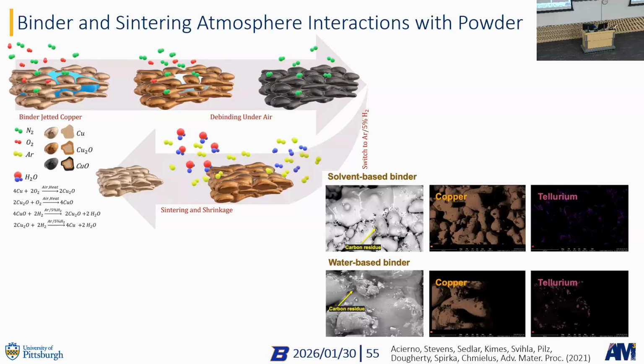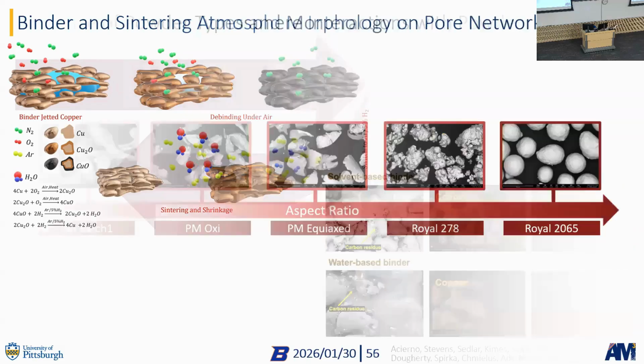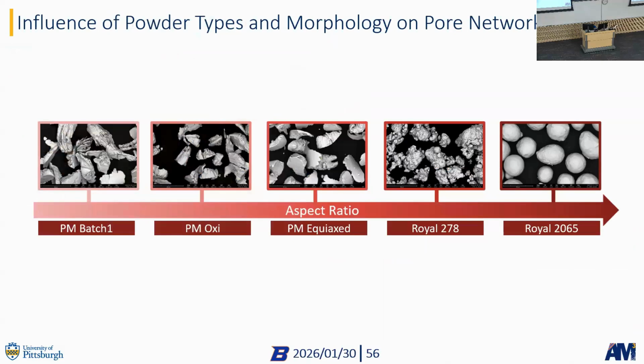We also looked at the binder and figured out we used the wrong binder from the start, right? A different binder resulted in much less carbon and oxygen contamination. And then we also thought, well, the gas atomized powder is very expensive. So let's work with some local manufacturers of powder and get super cheap powder. These powders here are actually machine powder. They're basically chips coming from a lathe, right? So super chunky powder. And we tried all kinds of aspect ratios, from super chunky to spherical.